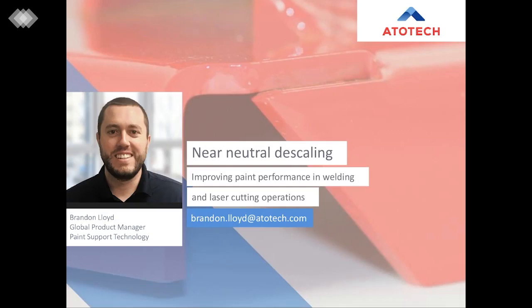Applying these very high quantities of paint can also lead to undesirable paint aesthetics, poor paint cure, and even loss of integrity of the paint adhesion qualities. And then lastly, the presence of the scale is really what leads to the poor adhesion. Applying more paint will not necessarily change the ability for the paint to bond to the substrate surface that is impeded by the scale. So the premature loss of the paint can really be a direct result of the poor corrosion itself.